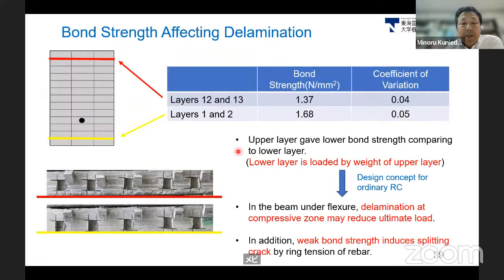And we also checked the interlayer bond strength at the bottom layer and the top layer of the beams. As you can see, the bond strength of the top layer is 1.37, but the bottom layer is 1.68. The lower layer provides a higher bond strength at the interlayers because, as you can imagine, the lower layer is loaded by the weight of the upper layer, so good bonding can be obtained.